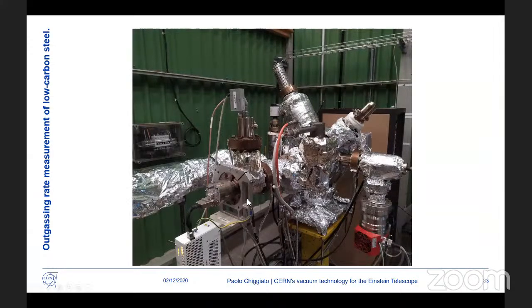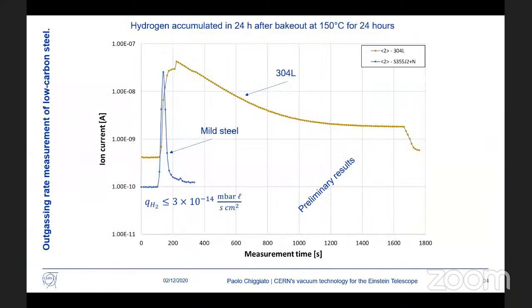This is a picture of the system. Here in front you see the spectrometer and the pumping units, and the vacuum chamber is on the left side of the picture. In the results we compare austenitic stainless steel 304L as received, I repeat, as received, and mild steel as received. These samples underwent a thermal cycle of 24 hours at 150 degrees, and this accumulation, done at room temperature, lasted 24 hours. What you see is really impressive: the blue peak related to the mild steel is extremely small, and mostly related to the movement of the valve.